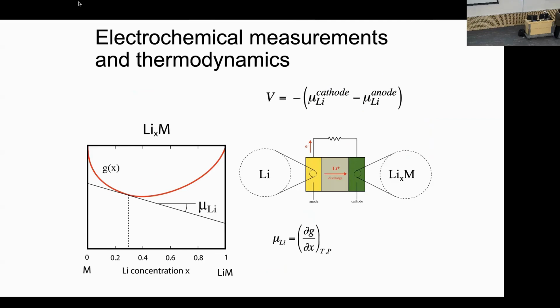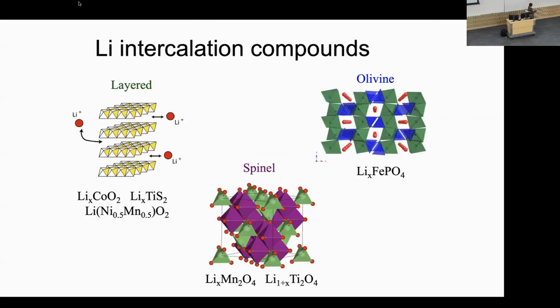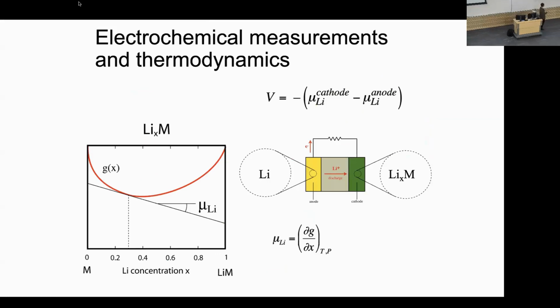So if instead of using graphite as your anode, you use metallic lithium as your anode, and then you use a material like one of those from the previous slide, so one of these, lithium iron PO4. This is just shorthand notation for all the other stuff that's in this compound. So this could be iron phosphate or cobalt oxide. If this is the material we're interested in, if we put this in an electrochemical cell of this form,